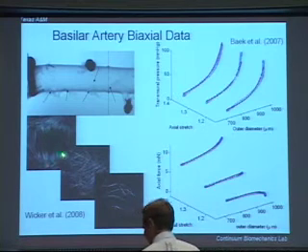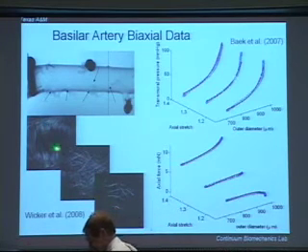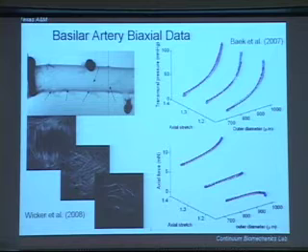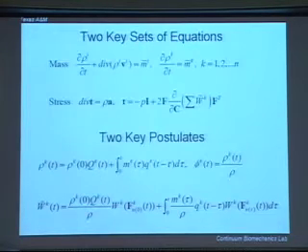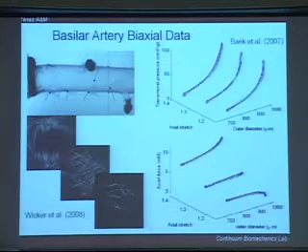We also use multiphoton microscopy to essentially survey this collagen orientation through the wall, as well as elastin. And that information then goes back into this model, so that we can not only say how much energy we store in a particular constituent as the vessel is deforming, but it depends on what the orientation of that constituent is, and we take that into account. So the red line simply showed that that equation can fit data at time 0 reasonably well.